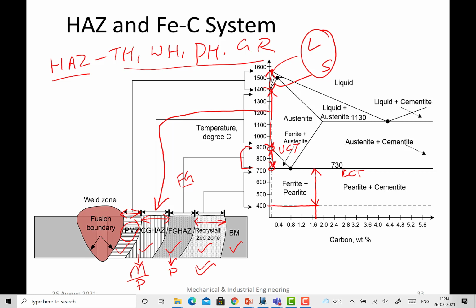So the point here is which kind of phases will be formed, that is a different thing, but these are the different zones that will be formed in a typical transformation hardening metal like steel, starting from the recrystallization zone to the fine grained zone, coarse grained zone, and then the partial melting zone. Whether it is solid state joining or fusion joining, in all these cases, depending upon the rise in temperature, you will have the formation of these zones, okay. So if the temperature is limited to say 1000 degrees centigrade, then you may have just the coarse grained zone, fine grained zone, and recrystallization zone.